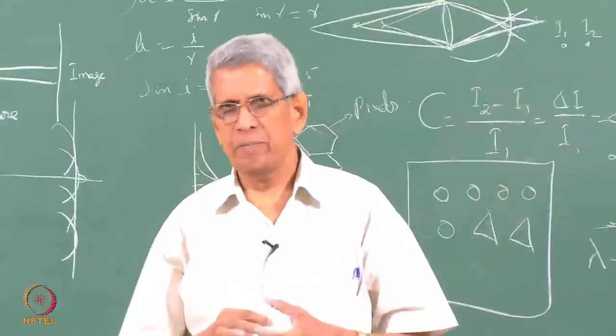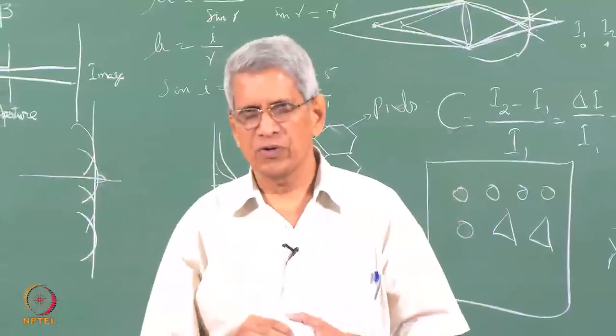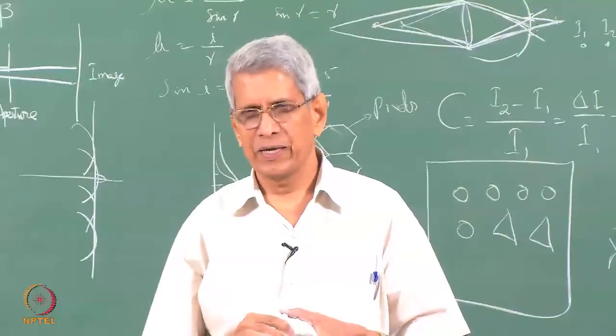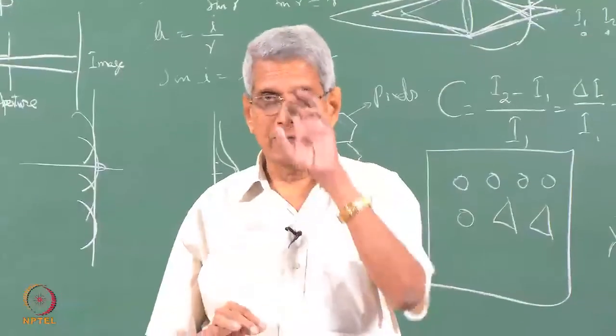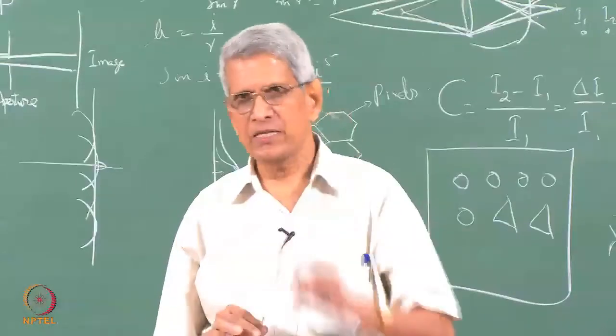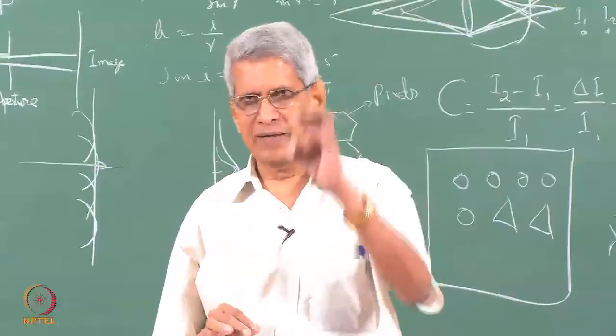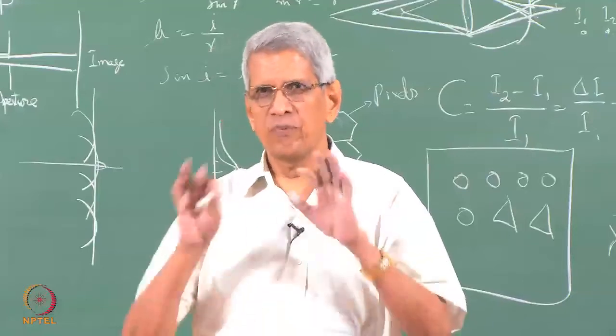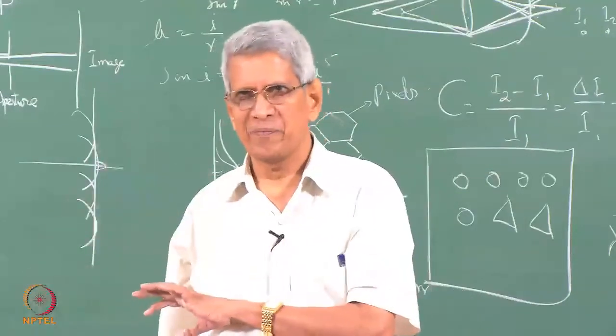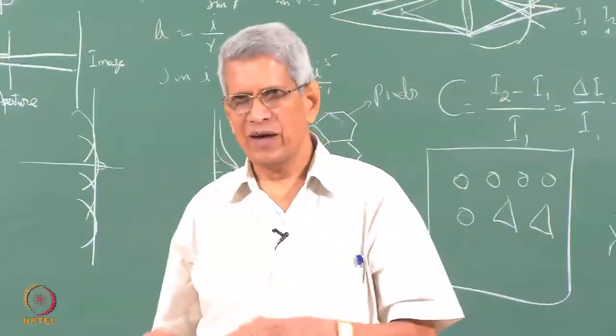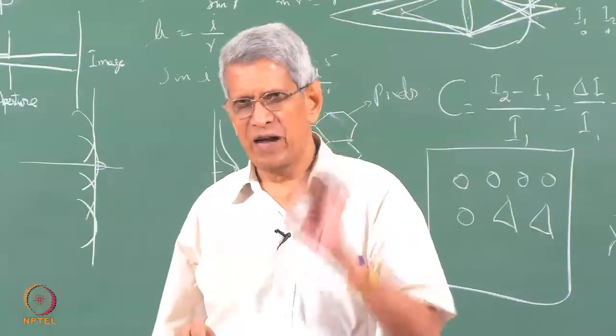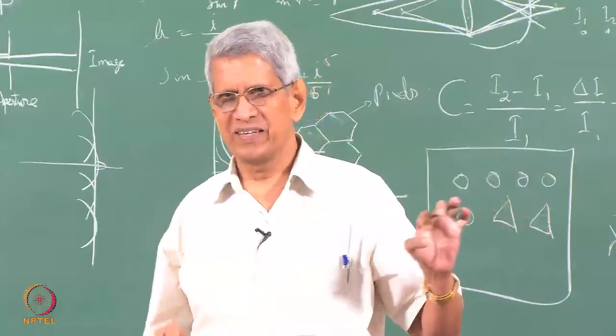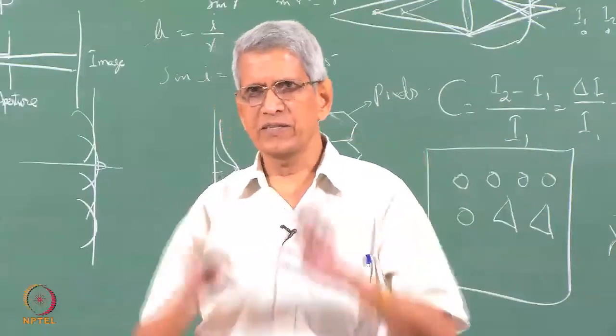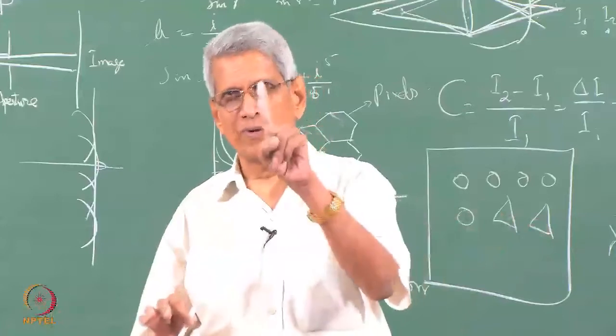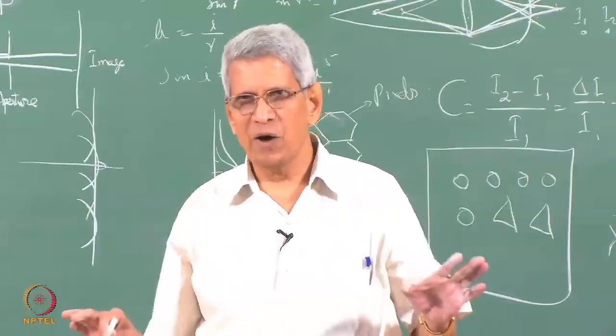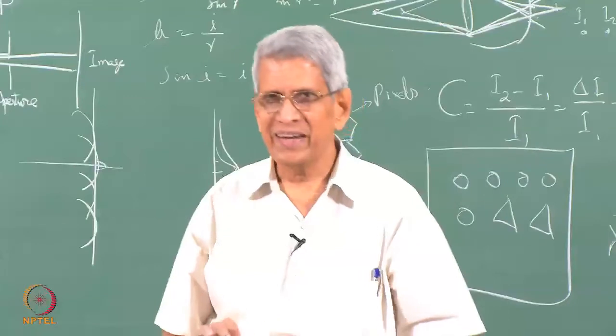If you look at that criterion, maybe a vacuum of 10 to the power of minus 4 torr is good enough. But when we examine the sample, contamination of the sample can occur because the electron beam is hitting it, and contamination occurs at some particular rate. If we want to avoid that, if we increase the vacuum to around 10 to the power of minus 8, minus 9 torr, it takes a very long time for a monolayer to form.